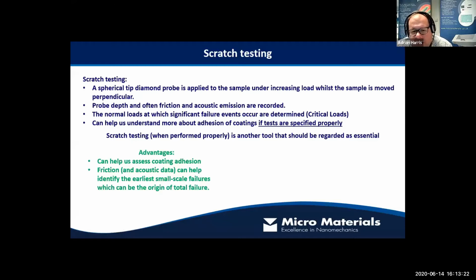So an advantage is the fact that it can help us look at the coating adhesion, which, as we said, we can't do through the indentation method. Friction and acoustic data can also help us to identify the onset of the earliest failures. Very often the total failure of a coating system can originate from a small, seemingly insignificant failure, which starts much earlier. And for us to be able to identify the onset of these early failures is very helpful.